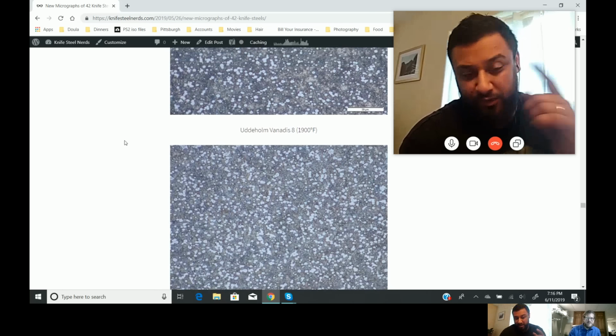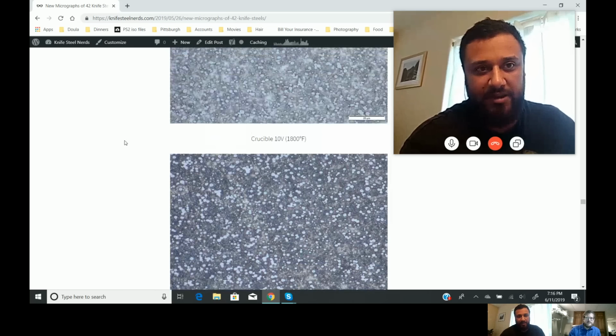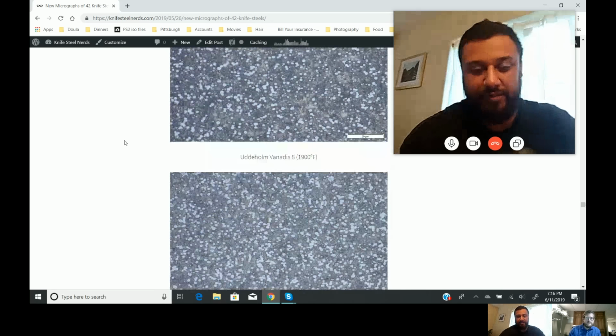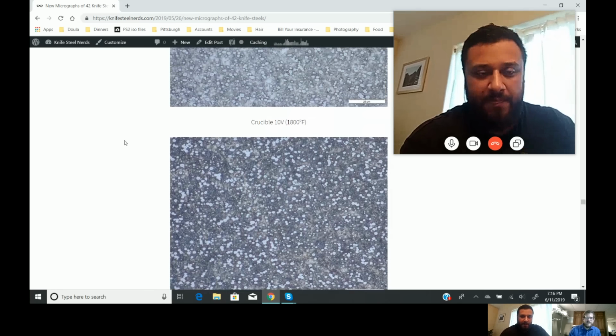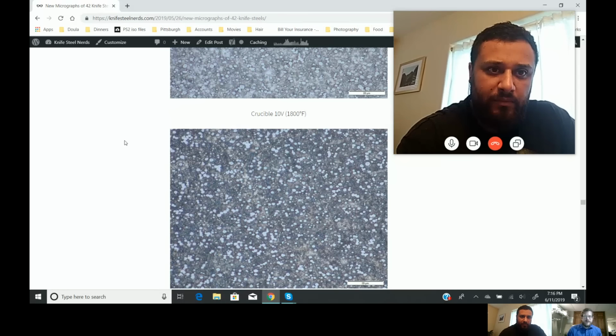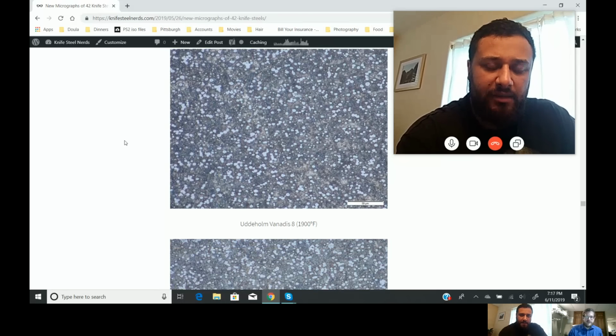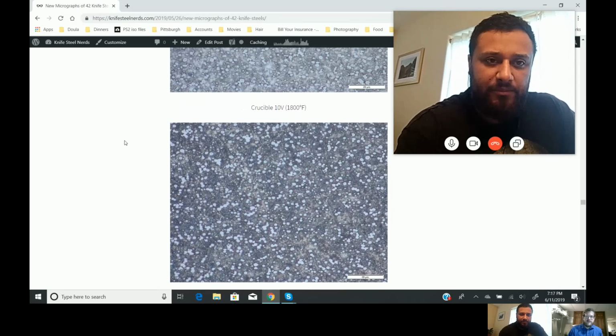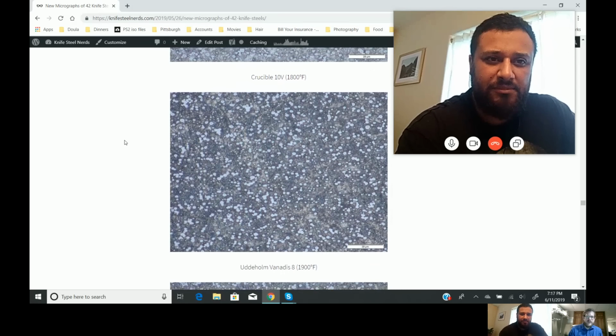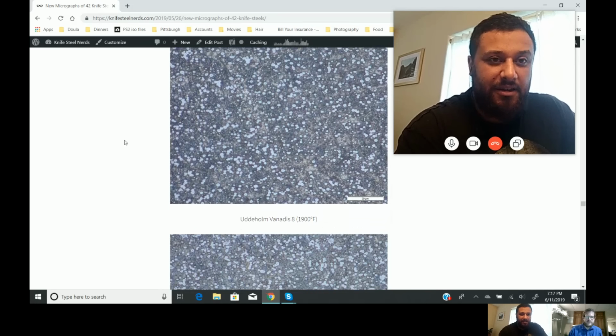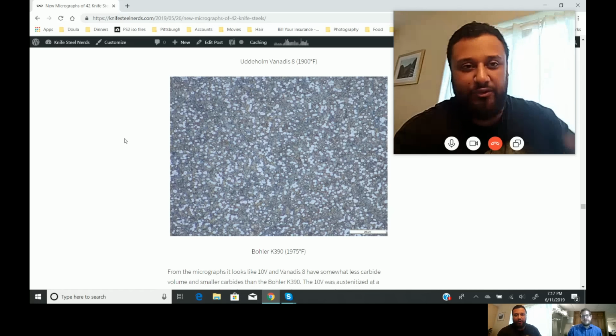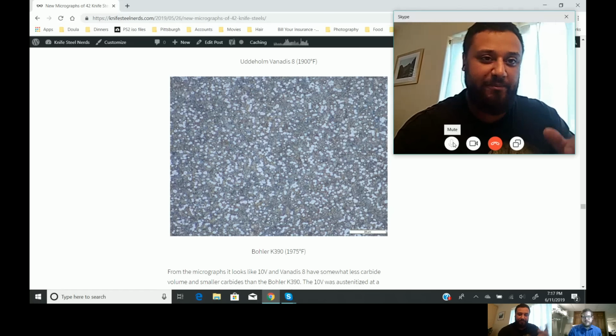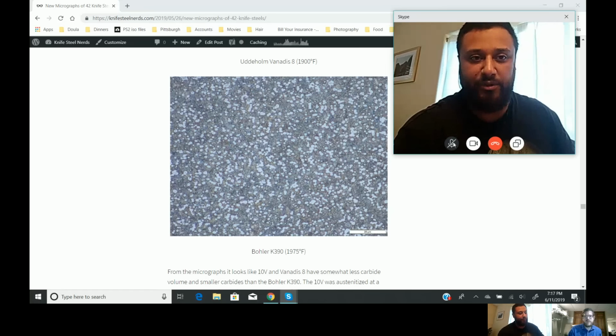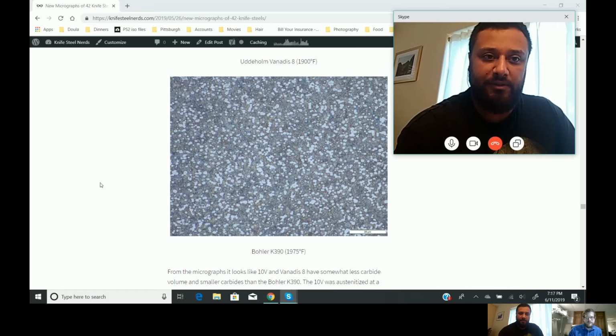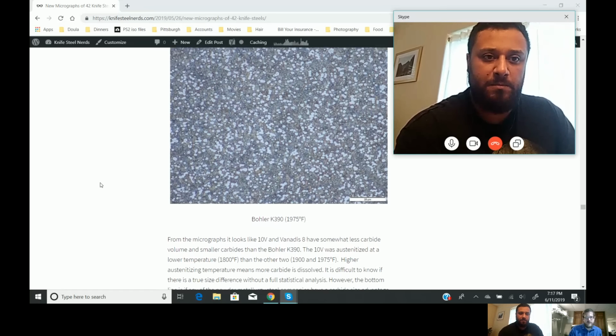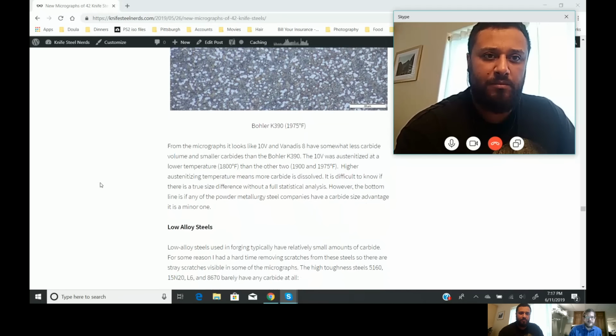Interesting. Now, there are some differences between these steels in particular. We see that they look kind of the same, but the one that stands out the most is that Vanadis 8. Yeah, Vanadis 8 looks a little bit finer than the other two to me, and I think that's just because it has a little bit less vanadium carbide. So yeah, it looks intriguing. Uddeholm claims a significant toughness advantage over 10V, so I'll be interested to test its toughness. Based on some patterns we're seeing, we might be safe to say that it could be a really nice sweet spot in between 4V and 10V when it comes to toughness. Yeah, it could be. And it only has a little bit less carbide than 10V, so if it does have a toughness advantage, it'd be an interesting one.